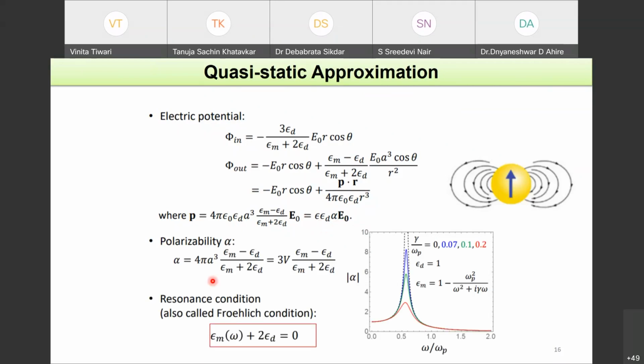Now, for a simple spherical nanoparticle, if you look into the expression for alpha, it has these terms, epsilon m minus epsilon d, where epsilon m is the metal permittivity and epsilon d is the dielectric permittivity. There will be a resonance when the denominator of this goes to 0. That is known as the Froelich condition. And when you plot alpha as a function of omega over omega p, you will see that when gamma, which is basically the damping, that is the loss in the metal, is increasing, the resonance is getting weaker and broader. And that is what happens for all resonators, the quality factor of the resonance goes down.